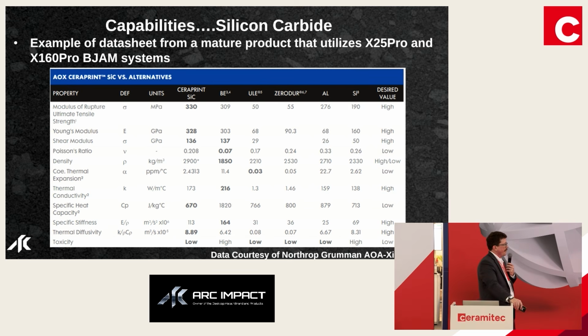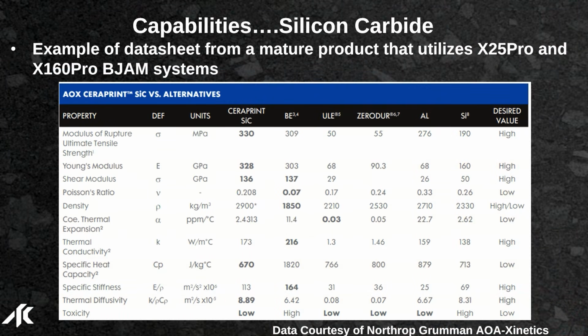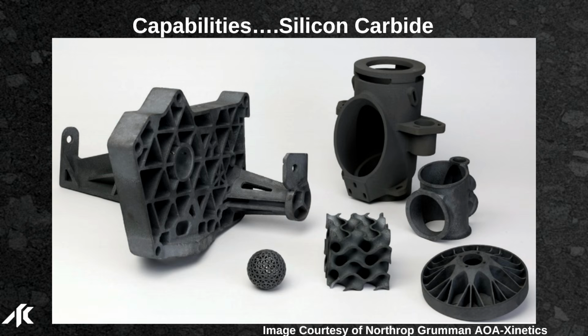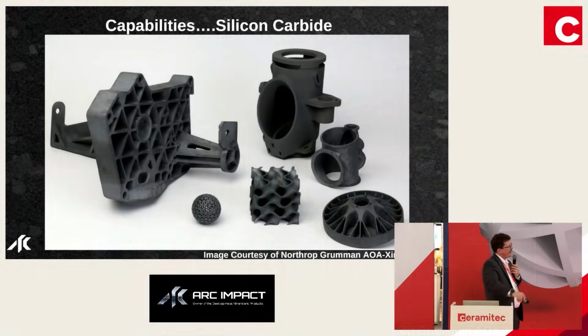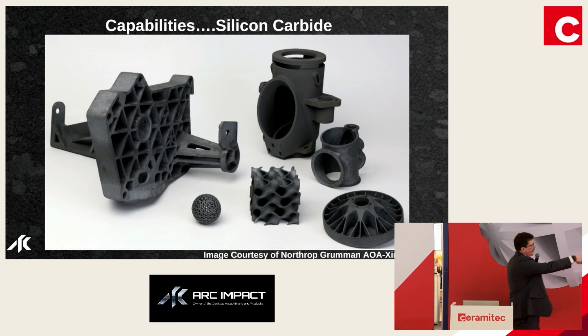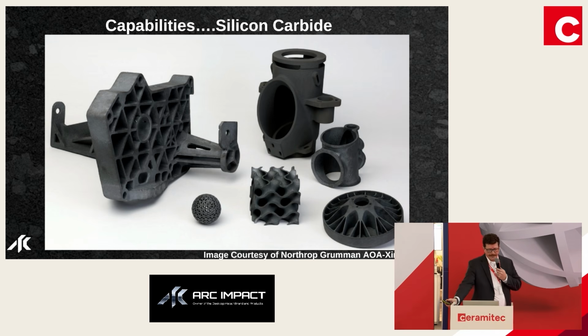But for their process, for their system, they see about 85, 90 volume percent silicon carbide, and these are the properties that they're seeing from that. These are the types of parts that they would produce. The bottom right there is probably something on the size order of what you do on the 25 Pro if you're not doing quantity. The big parts on the top left are something that you'd want to print on the 160 and could do quite easily and quite readily.